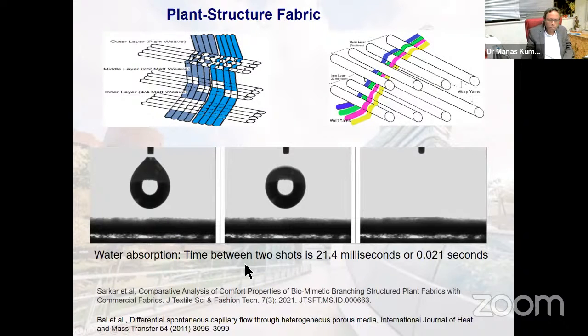This is the water absorption behavior we show here. The difference between each picture is only 0.021 seconds, that means 21.4 milliseconds. You can see a drop from the nozzle, this one is in the air, and this one has vanished. So its absorption is excellent.